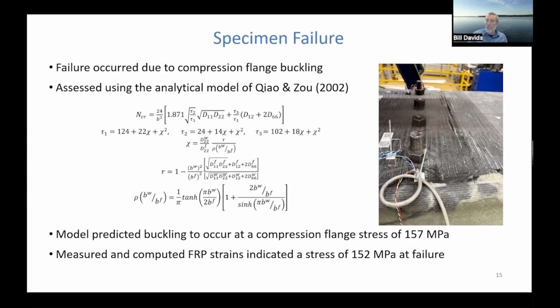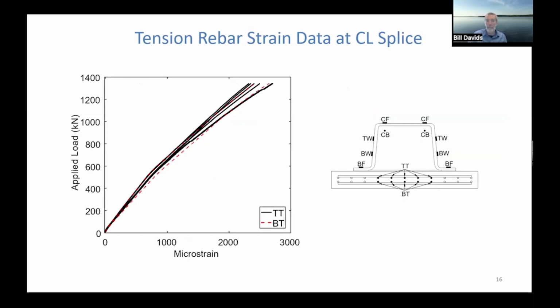We didn't anticipate buckling failure to occur because that wasn't predicted to be the first failure mode. We expected yielding of the reinforcing or perhaps failure of the concrete ridges, but it actually went to a much higher load than expected and it failed in buckling.